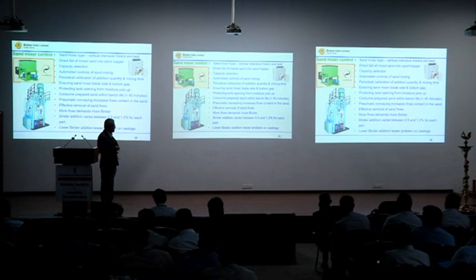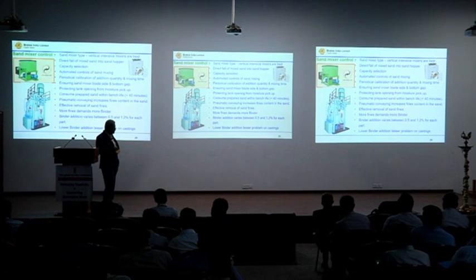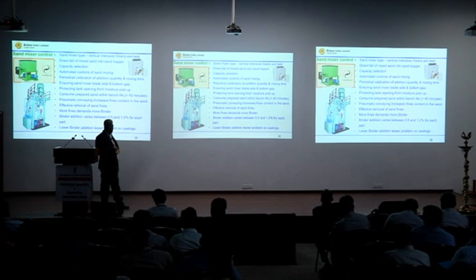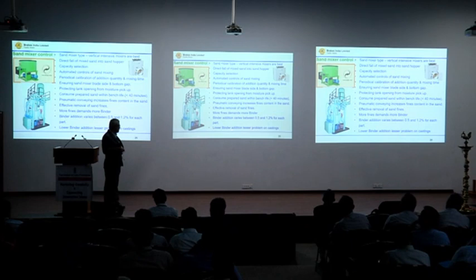Pneumatic conveying of the sand increases the fines content, so it is better to separate the fines by effective removal. We have to find a way to remove the fines, because more fines demand more binder. The normal binder addition varies between 0.5 to 1.5% of sand part, depending upon the quality of the sand. Lower the binder addition, lesser the problem on castings.